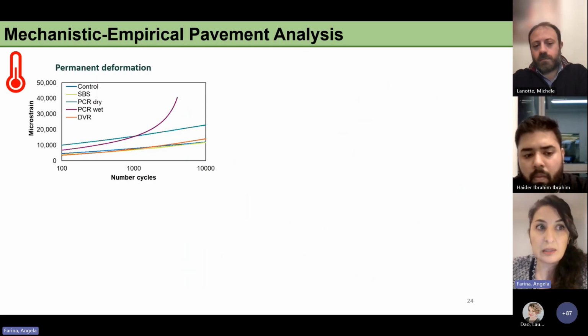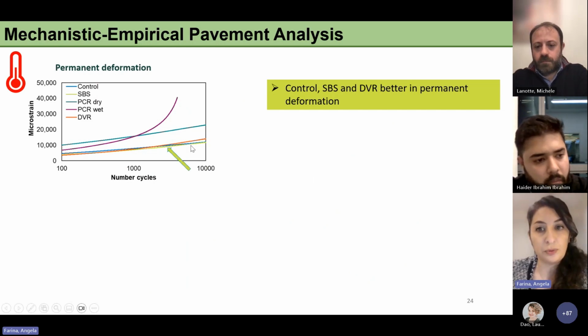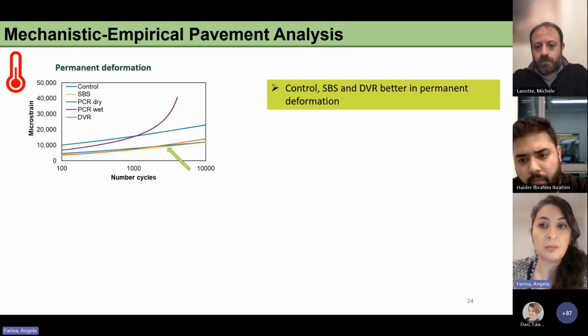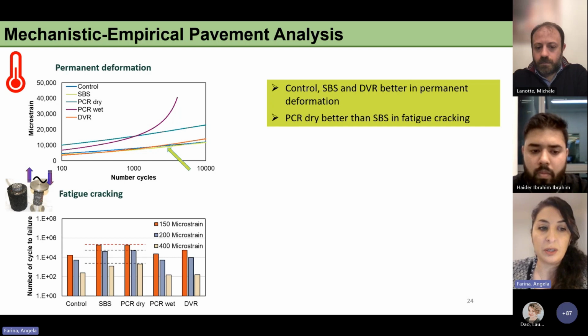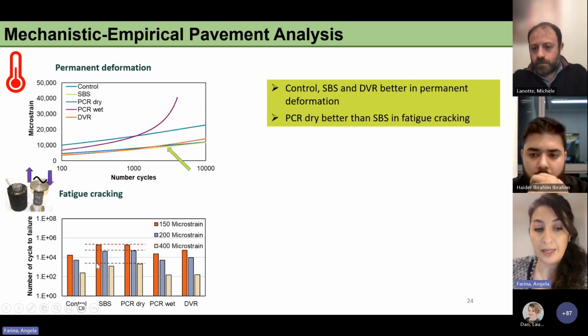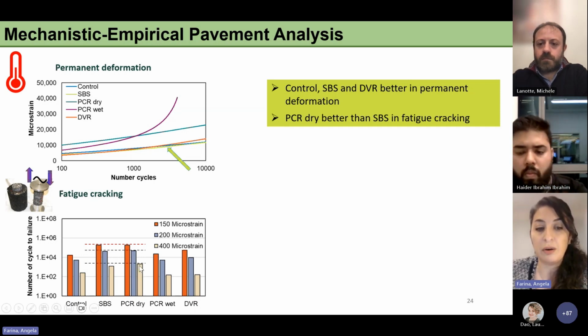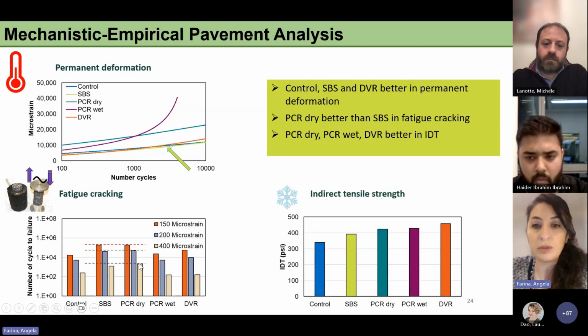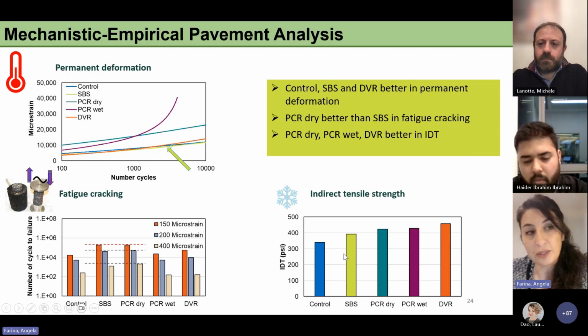So in terms of results for the permanent deformation, we can notice that control, SBS and DVR mixtures perform better than PCR dry and PCR wet. However, for the fatigue cracking, we can notice that the PCR dry performs as well as the SBS, and also better than the SBS when we consider higher level of microstrain. And in terms of thermal cracking, the mixtures containing scrap tires perform better than the references.